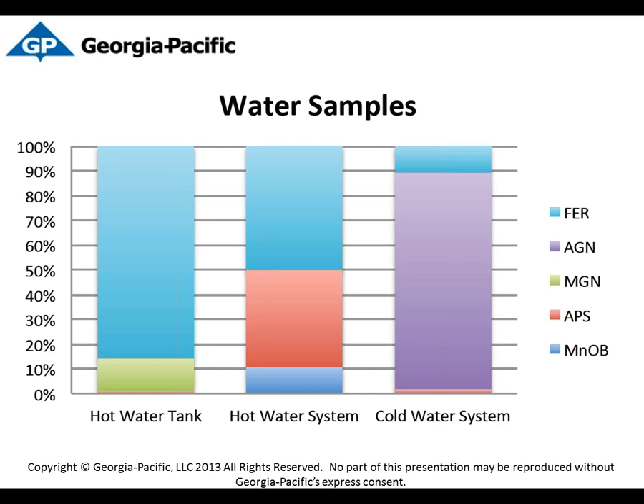And then once we got DNA a little more involved in our systems, at this point in time, this is months and months and months after we first recognized we had MIC, we started looking into more and more species, just as we learned about the system and looked at parts of our system to see what's present in each part. And the biggest one that kind of shocked us was the fermenters, the big blue bar you see there. You can see how in the hot water tank we have an extremely high concentration of fermenters as compared to the hot water system and an almost non-existent cold water system. So although all 3 of those systems are fed by the same water, there are strikingly different concentrations of bacteria in each system.